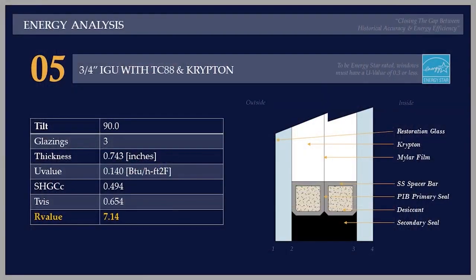Now we take the exact same 3/4 inch insulated glass unit, but instead of using argon, we install krypton. The R value skyrockets to 7.14. The U value drops to 0.140, which is remarkable.